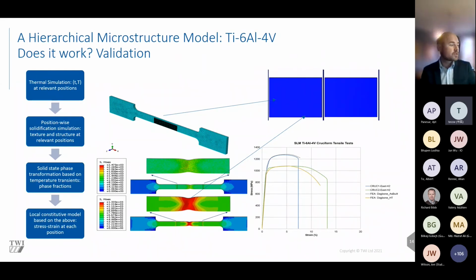And this can help us start to understand that link between the process conditions and what kind of heat treatment we might need, which might be very different from a conventional heat treatment for Ti64. And this is activity that industry is starting to use. They're really wanting to minimize the amount of trial and error experimentation and understand how they can get consistent and homogeneous properties throughout their build, which might mean tailoring the process parameters to geometric features or as the height gets bigger in the build chamber.